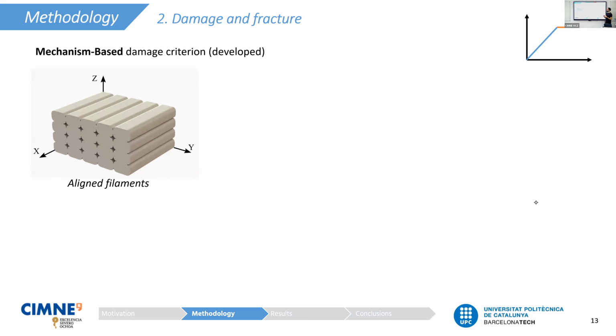Therefore, what we have done is we have developed a mechanism-based damage criterion. In this criterion, we're expressing one stress factor different in each direction. For instance, we have these filaments that are aligned in the x direction. Therefore, the failure is different in the x direction than in the y and z directions. For the x direction, if the ratio of the normal stress in the x direction to the strength in the x direction is higher than 1, we indicate that this material is failing. However, this is only for the case where the stresses are positive, meaning that the filaments are under traction.